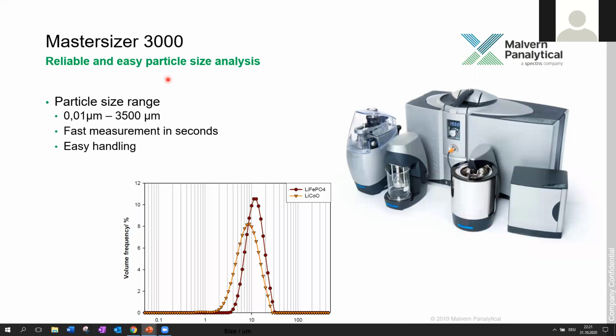You can do it with this instrument from us, the Mastersizer 3000. And here you can see the particle size distribution. It's really easy. You put your material in the tank, and then the instrument is measuring. You can determine particle sizes from nanometer up to 3500 micrometer. Here we can see two cathode materials. This is lithium iron phosphate, which is a little bit more than 10 micrometers. And we also have lithium cobalt oxide, which is a little bit smaller.